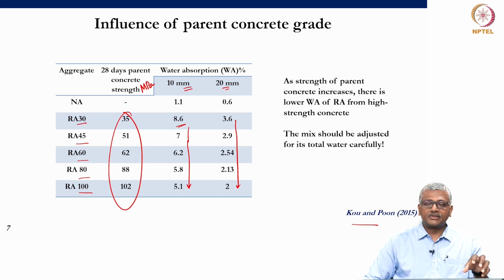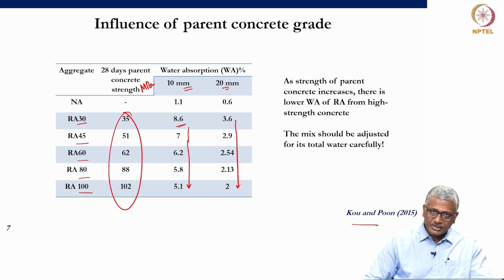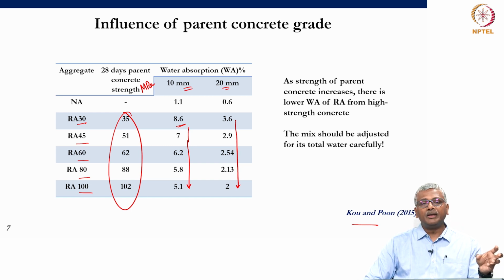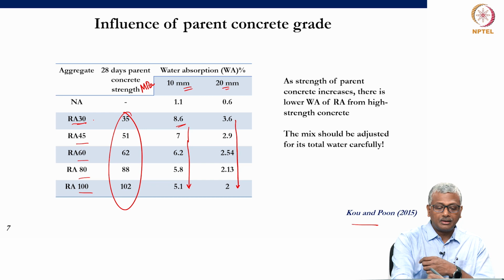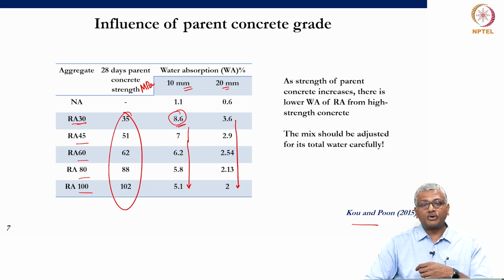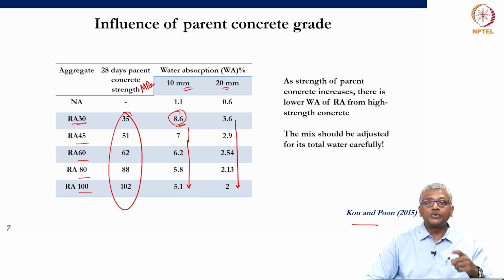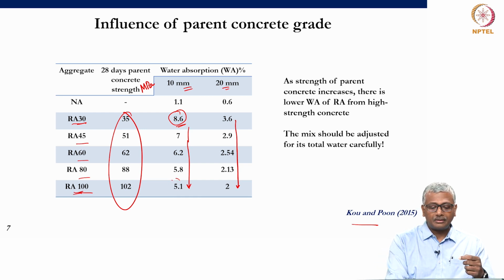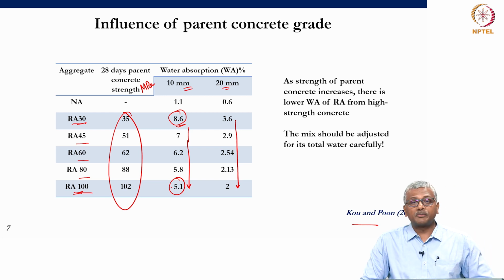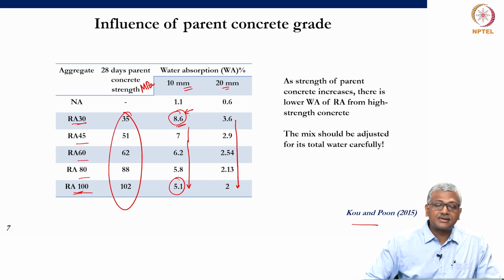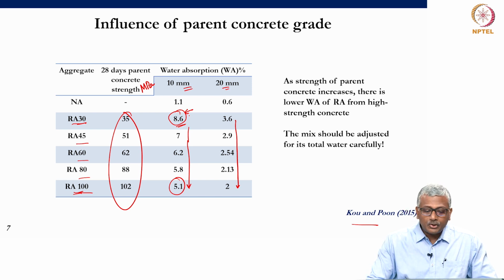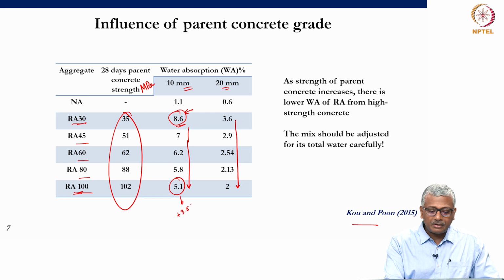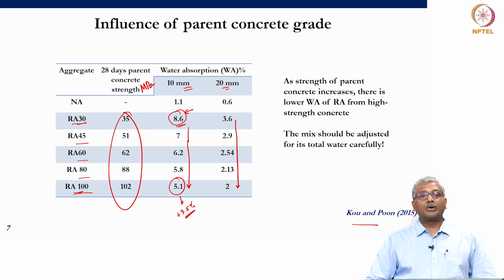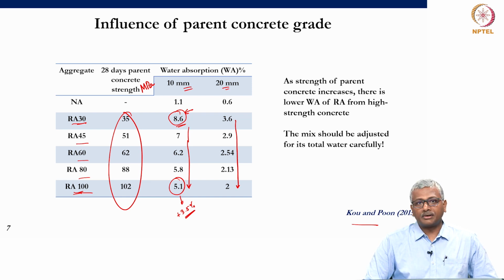So, this tells you that when you have coarse aggregates from different sources, if you have not done a source characterization, if you do not know what kind of concrete it is coming from, you need to be very careful about adjusting your mixing water. Because imagine if you make concrete with this aggregate, you have 8.6% water absorption for your 10 mm. But if your aggregate source now changes to a higher strength parent concrete, then your water absorption is dropping. Now, if you continue to add so much extra water to your system, that means you are adding, let us say, about 3.5% extra water when your aggregate source is changing to the higher strength concrete. That means you have excess water in your concrete and your strengths will come out to be lower.